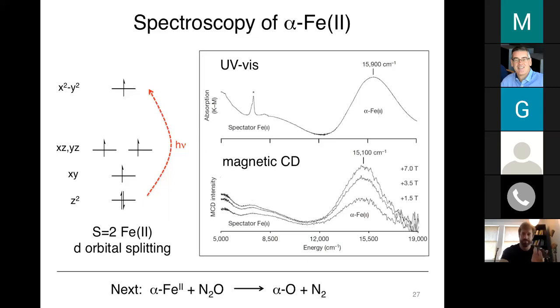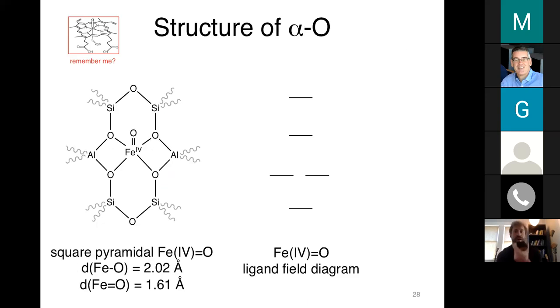So now what we're going to do is take alpha iron and transfer an oxygen atom from N2O into this vacant axial position to form alpha oxygen. So again, I'm kind of giving you the answer, but a big deal for my PhD research was actually understanding the structure of this alpha oxygen site. And what we found was that this was an iron(IV) oxo site with an axial oxo ligand, the iron-oxo interaction being very, very strong.